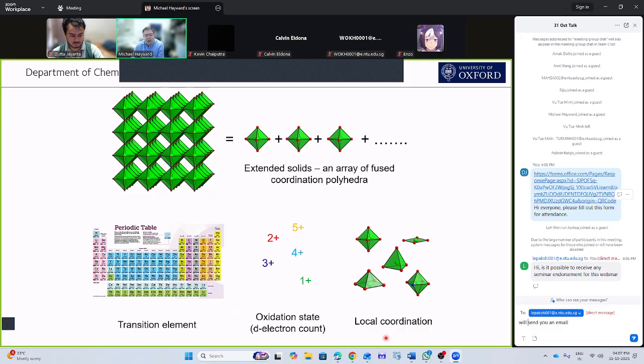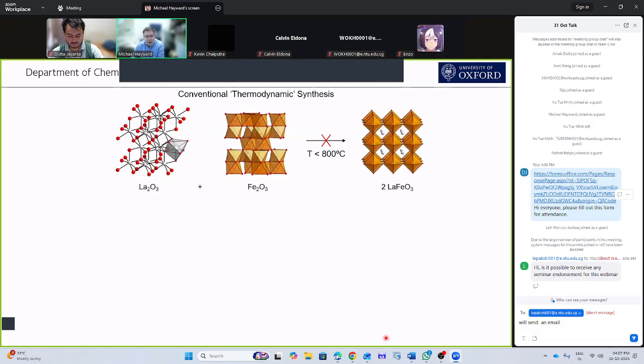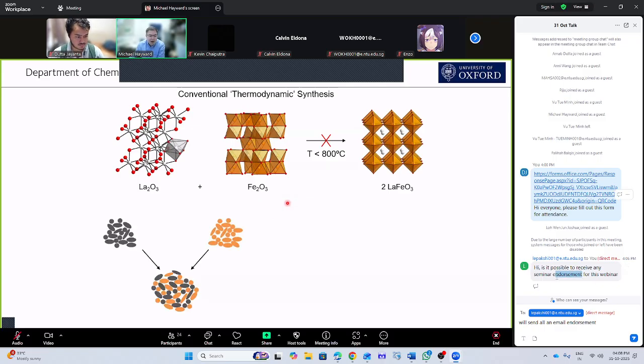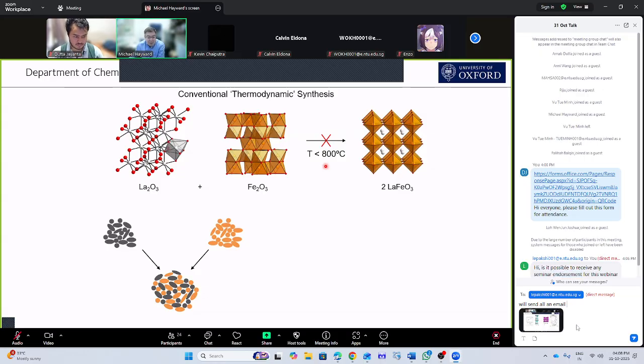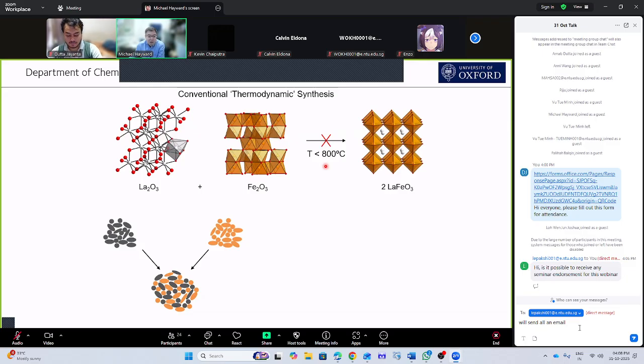And as soon as we try and do that, we realize we run into a problem. And the problem is to do with solid state synthesis. So if we consider a simple synthesis of a ternary oxide, so two metals and oxygen. So we take this lanthanum iron oxide example, we could consider making this compound from the simple combination of the binary oxide, so lanthanum oxide and iron oxide. And so what I can do is take the two powders and mix them together. And what I see is that nothing happens. I just have a mixture of the two powders. I need to heat the system to at least 800 degrees C to get a reaction, and more reasonably 1000 degrees C to get a reaction at a reasonable rate.